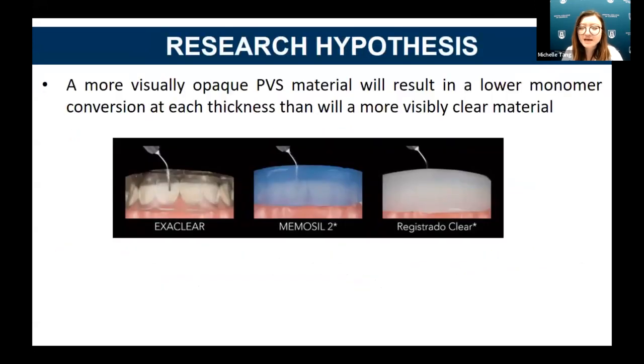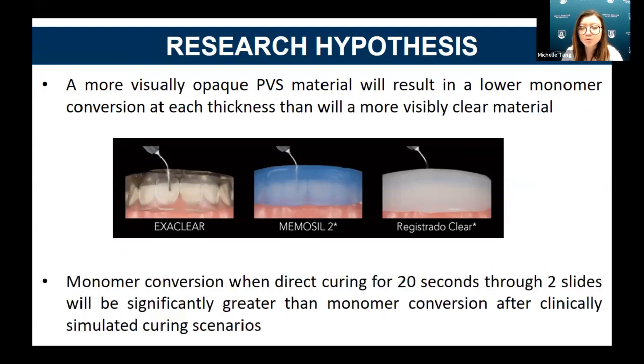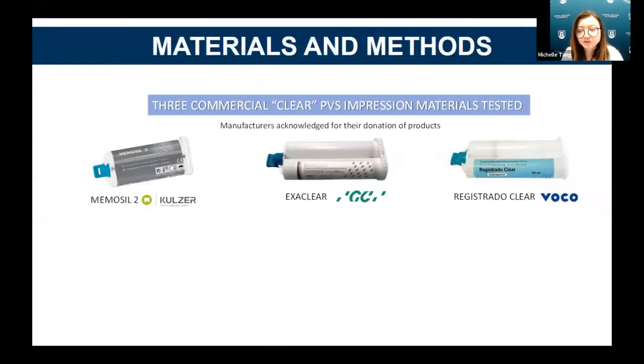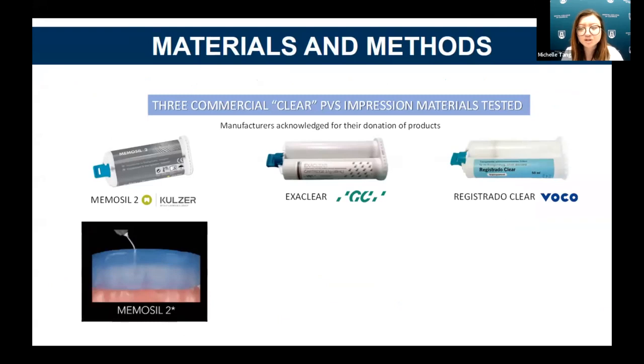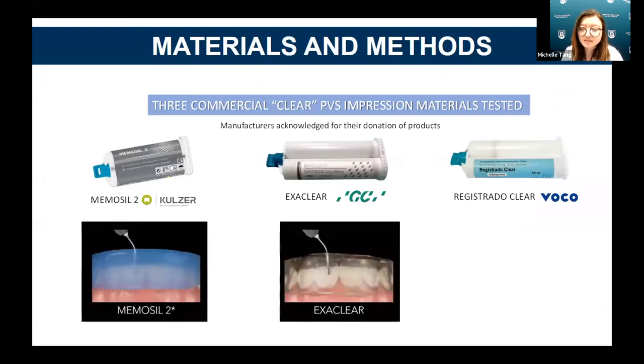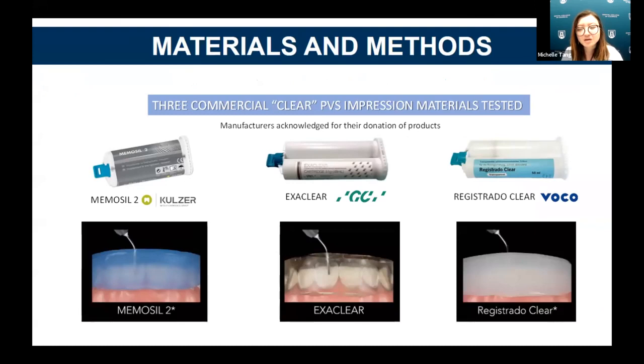It was hypothesized that PVS materials appearing more opaque to the eye will result in a lower monomer conversion, or be less cured, at each thickness. Furthermore, conversion with direct curing for 20 seconds through 2 slides, or the control group, would be significantly greater than the conversion in the series of clinically simulated scenarios. To understand the second hypothesis, we'd have to delve into the methods of our research. The 3 tested PVS materials were the following. Memosil 2 by Kulzer showed a blue tint, GC Corporation's Exaclear was transparent, and Voco's Registrado Clear was a translucent white.